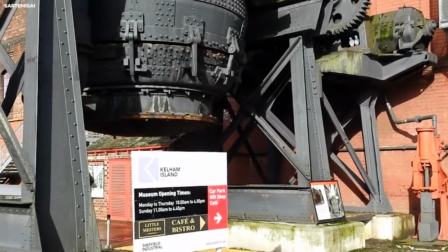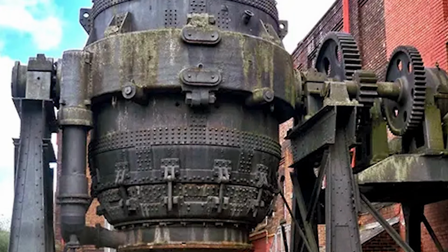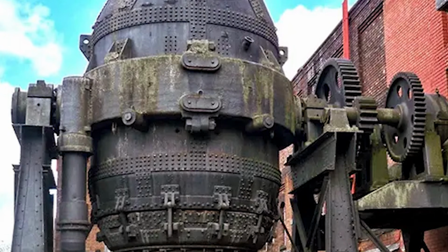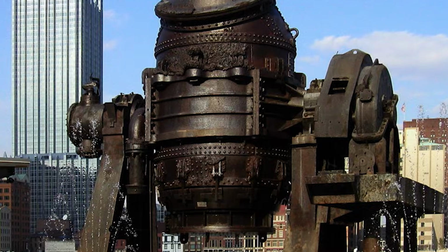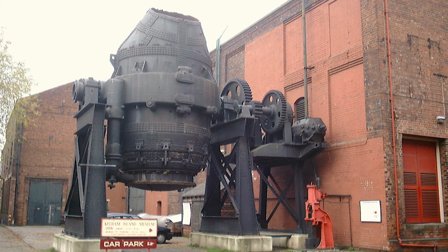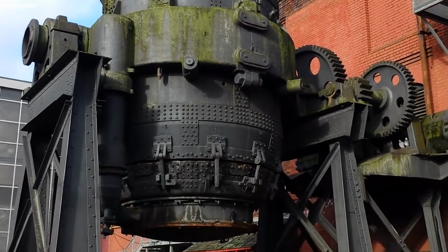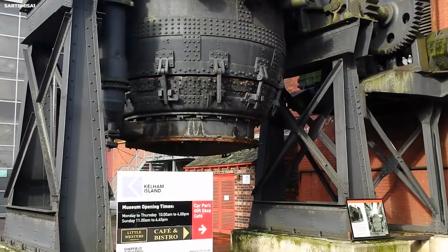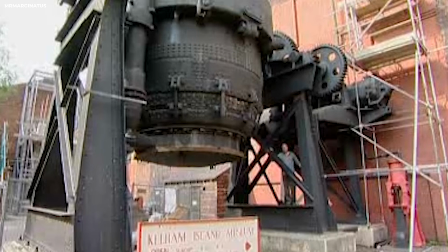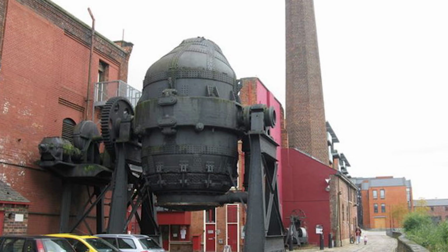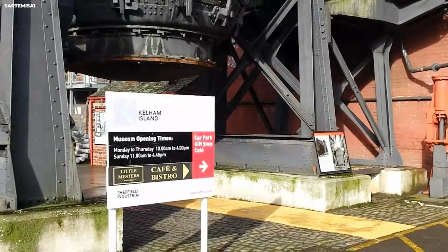At its core, the Bessemer converter was a massive, pear-shaped vessel lined with refractory material and mounted on pivots. Molten pig iron was poured inside, after which powerful blasts of air were forced upward through the liquid metal. This air burned away carbon and impurities, rapidly converting iron into steel. The reaction was violent, spectacular, and extremely unpredictable. Temperatures exceeded 1,600 degrees Celsius, and the process produced towering flames, blinding light, and showers of sparks.